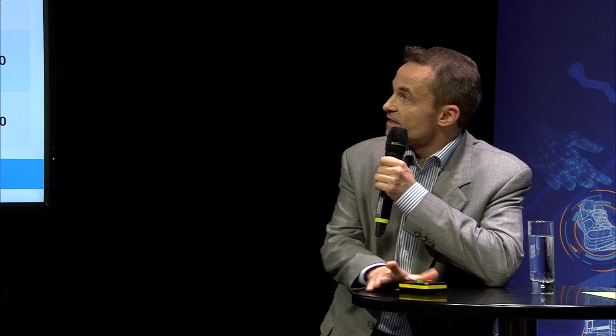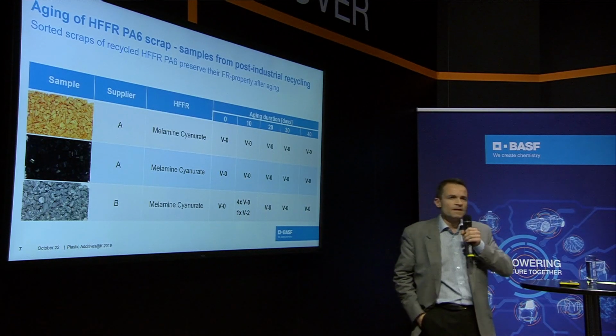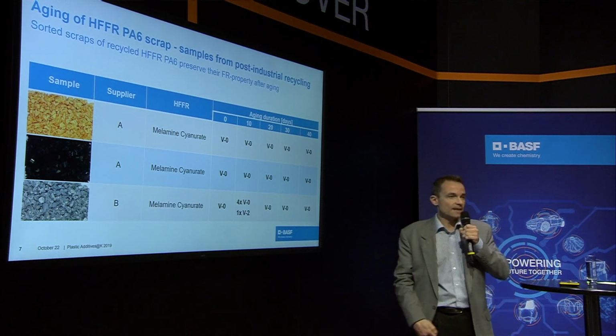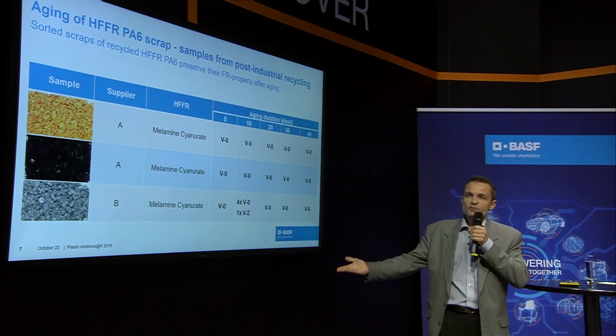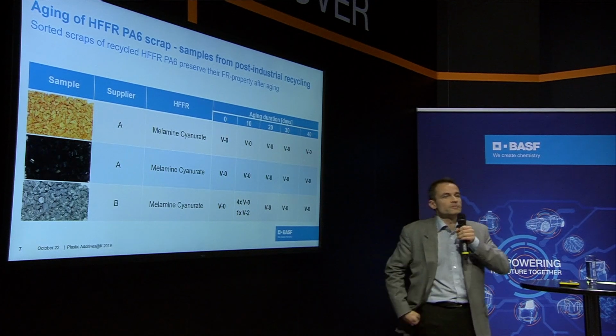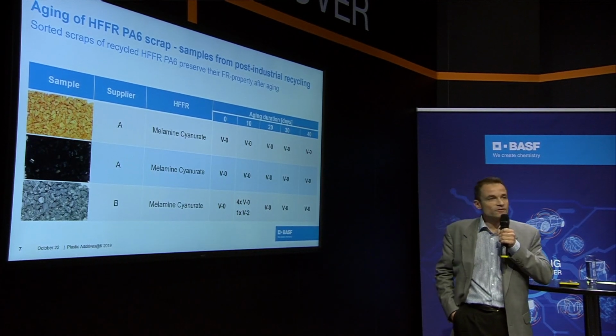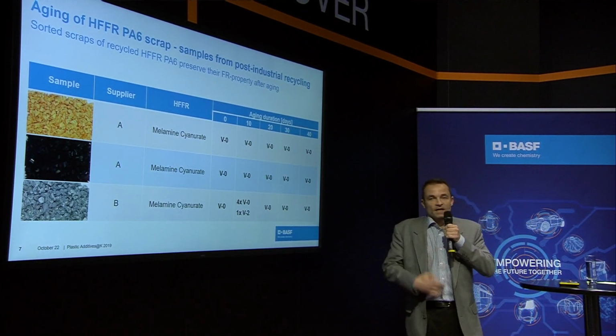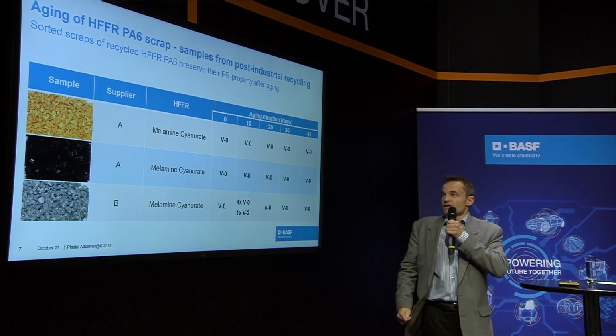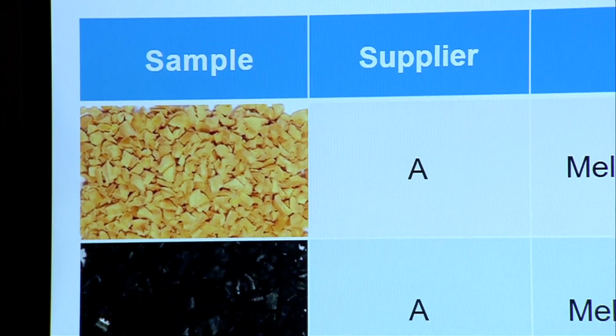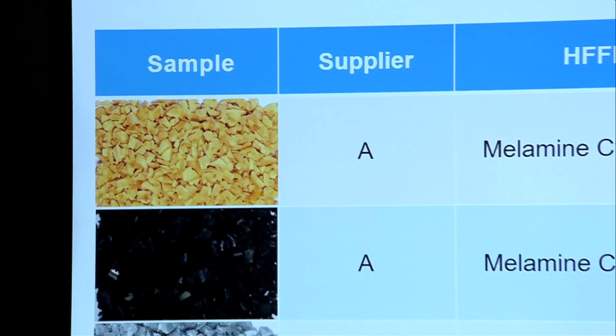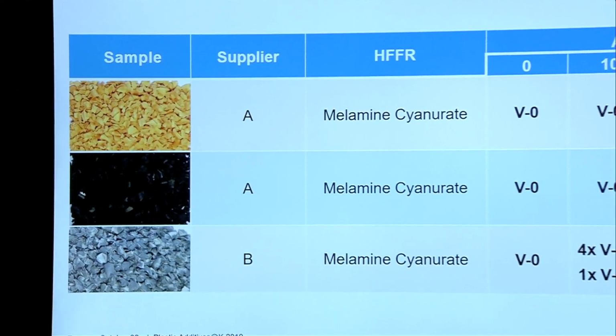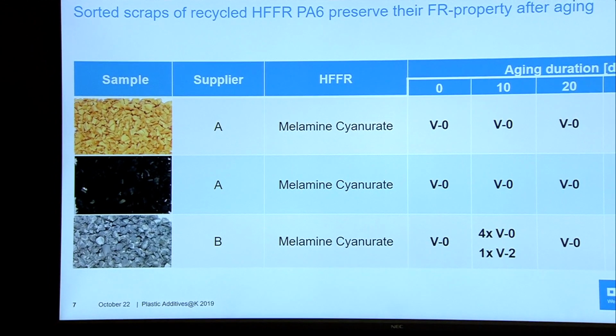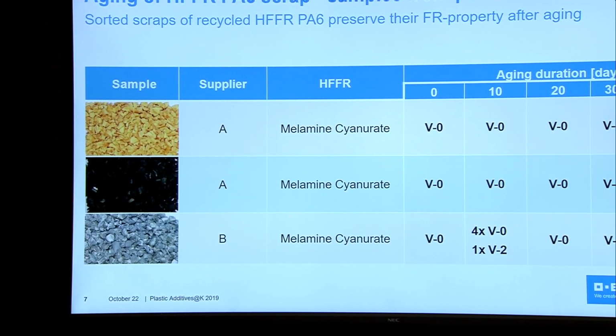Still with polyamide 6, now oven aging. In this case, we went beyond lab scale tests in the sense that we received post-consumer scrap from 2 different companies, so something already realistic. You can see supplier A and B. The oven aging took place at 120 degrees during 40 days. And you can see that the V0 level was also maintained in this case.